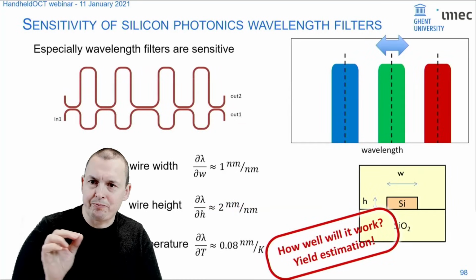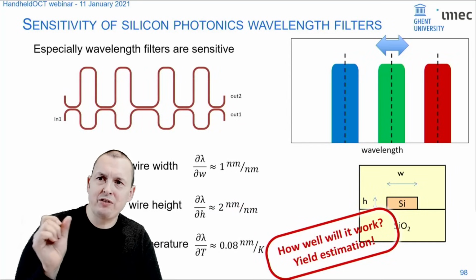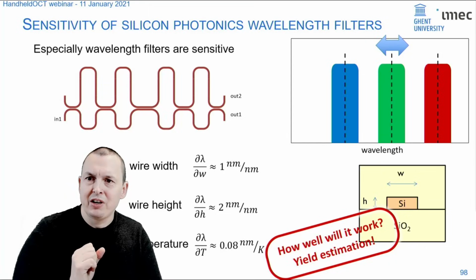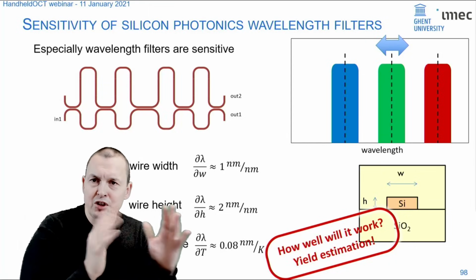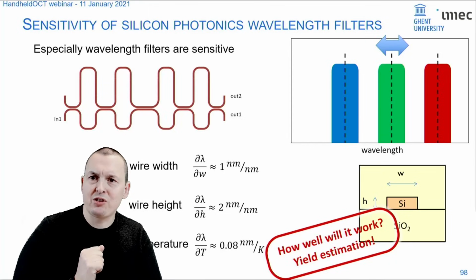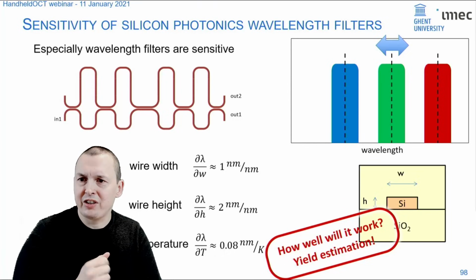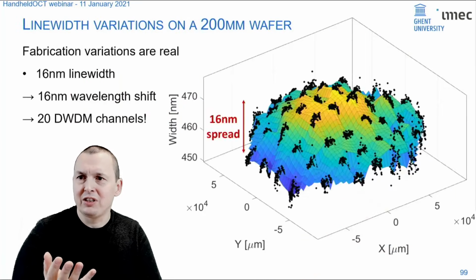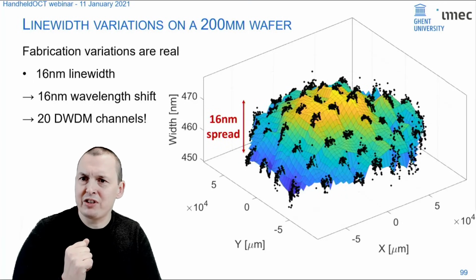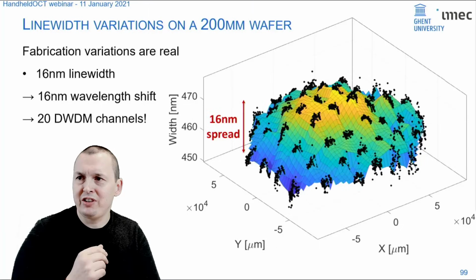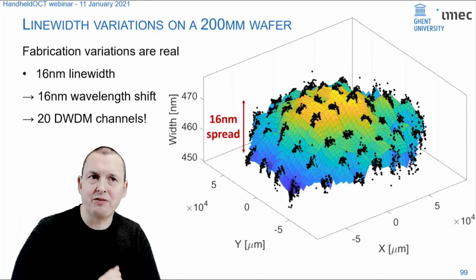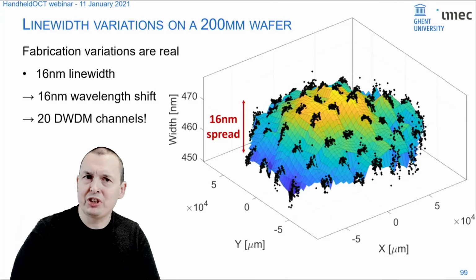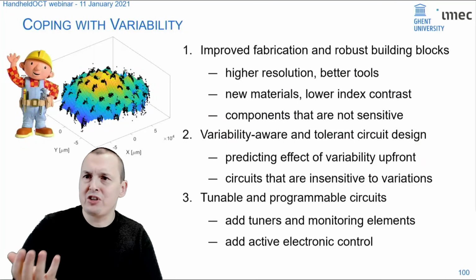Just as an example, if you change the width of your waveguide by 1 nanometer, your filter response will shift by 1 nanometer, which is already a few communication channels in a telecom network. And then if you look at actual variations on a wafer, this is a wafer of a couple years ago, you see that within a wafer we can see 16 nanometer of line width variations. That's an enormous shift. So how do we cope with such variability?